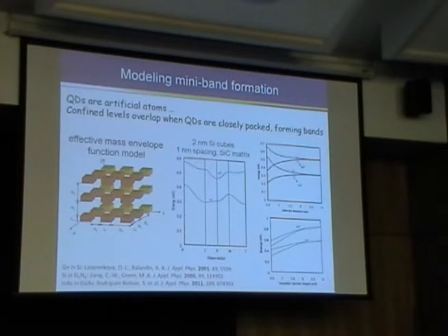The other thing is that here's a plot of energy versus the barrier height. So what I'm showing here is the interdot distance, which is the first thing that I described. Showing here is lowering the insulator barrier height. If we bring the barrier height from 3 eV down to 0.5 eV, we see not only a reduction in the energy of the system, but we also see opening up of bands for both of those particular states. They're not as wide as these. The dominant effect is really the interdot distance and not the barrier height, at least for the numbers chosen here. But it gives you an intuitive sense for what to expect in the ideal situation.